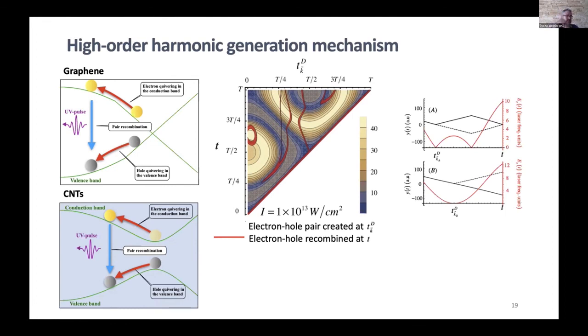As a result, the high harmonic spectra from these low dimensional carbon allotropes are more intricate, not as regular as in atoms or molecules. Finally, as we can see here, the cutoff prediction given by the semiclassical model, which is expressed by the red circles, is in excellent agreement with the results of the numerical integration of the time-dependent Schrödinger equation, which are represented by the blue diamonds.